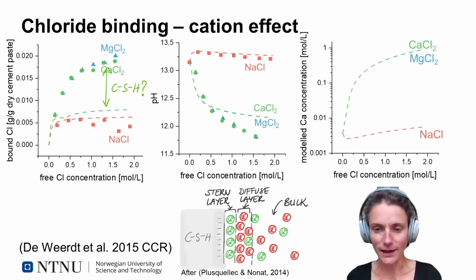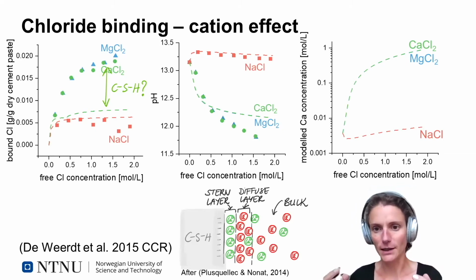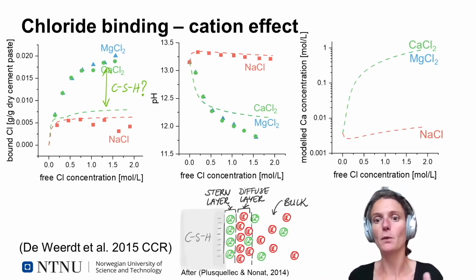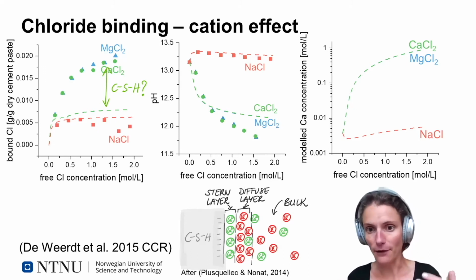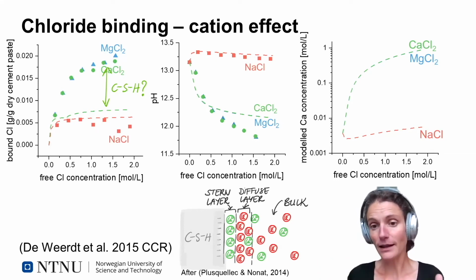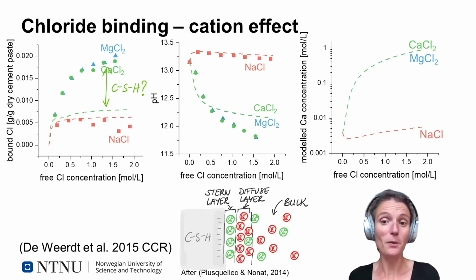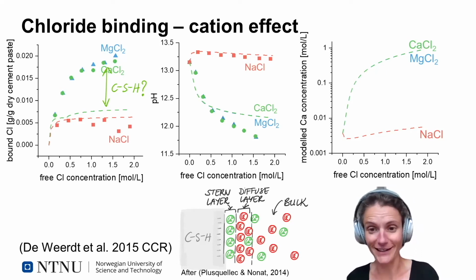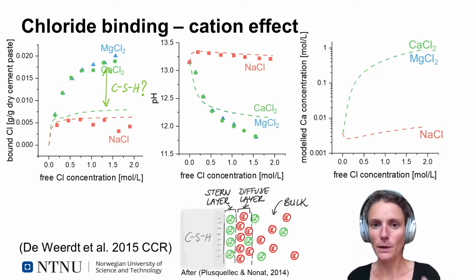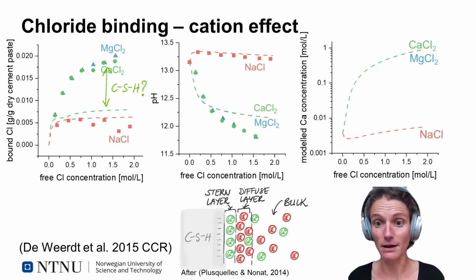So according to the electric double layer theory, the CSH surface is negatively charged and it will attract positively charged calcium ions in the Stern layer. If you have a higher concentration of calcium, we will have more calcium in the Stern layer. And then in the diffuse layer, these positively charged calcium ions will attract in their turn negatively charged chloride ions to charge balance. So we will have an accumulation of chloride ions in the vicinity of CSH. So what we're seeing here matches quite well with the ideal theory, though this remains to be confirmed experimentally.